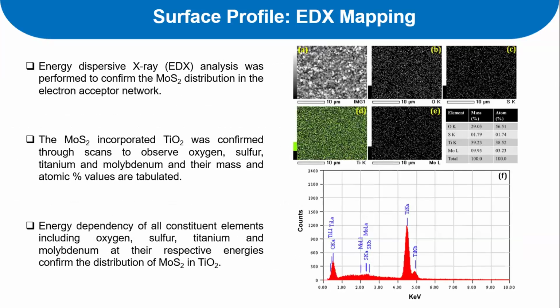So that is confirmed, and for further confirmation that it is moly sulfide, we went for the energy dispersive X-ray analysis, which shows the existence of the layers everywhere in the electron acceptor. The electron acceptor in general is a large area material. We can have 1 square centimeter of material. So we need to make sure that the 2D layered semiconductors are conformably covering the entire surface of the electron acceptor. So it is essential to study the energy dispersive X-ray analysis in multiple places, so that we can make sure that the components are there. In this particular case, we have confirmed that molybdenum and sulfur are present along with oxygen that is coming from the titanium dioxide itself. So it is clear that the moly sulfide is present everywhere on the titanium dioxide.